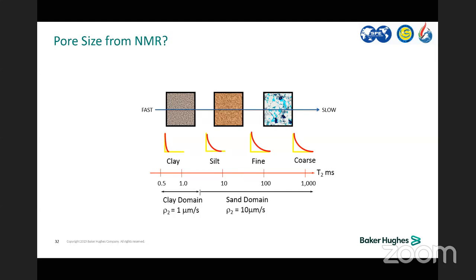The second factor for T2 is the pore size. If you have a large pore space, you get more time for polarization and relaxation. If you have a smaller pore, the relaxation is a very fast decay. In a shale, the decay is very fast because the pores are very small and filled by water, and there is no room to take time for relaxation. If you have a large pore space, you take a long time to relax.